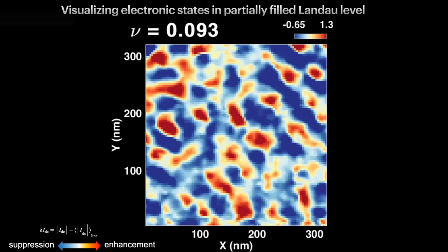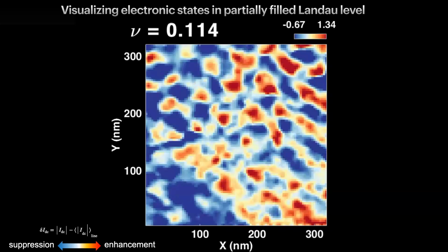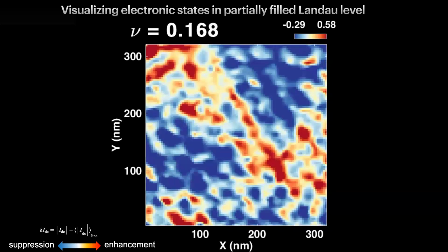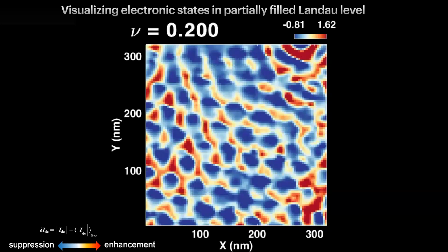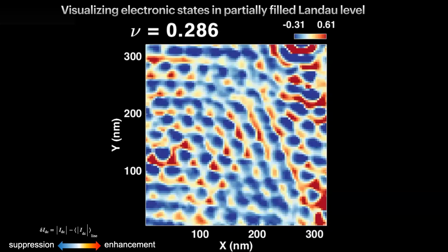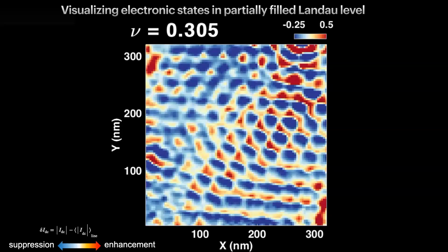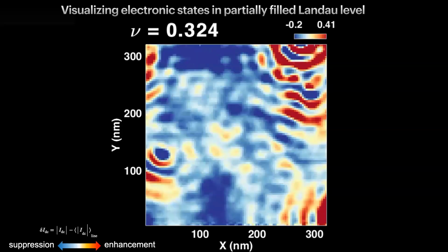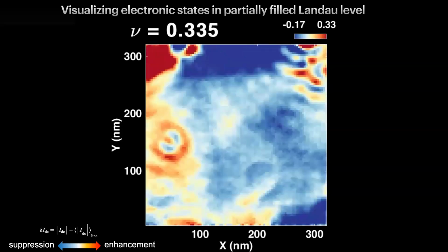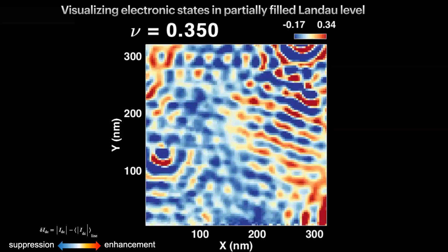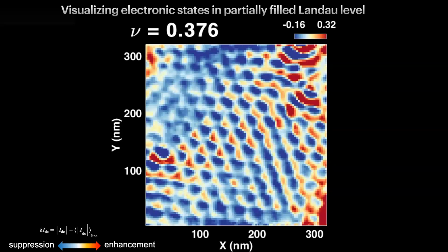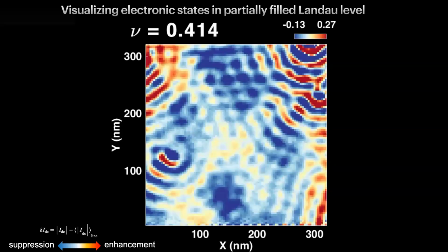And what you're looking at is what this current looks like, whether it's enhanced or suppressed, where enhanced is red, blue is suppressed, at very low filling of this Landau level. So 1 is when you have the filled Landau level. So let's watch the movie where we tune the density. And as you'll see, as you start to pack more electrons into this Landau level, there are these structures that emerge in the data. And what you see is a very organized structure in which at some fillings, like here, you have an extremely organized lattice, and then 1/3, remember what that is? That's the Laughlin state. You get craziness, then you go back as you fill the density, and you see organized structure. So there's a lot in this data set.